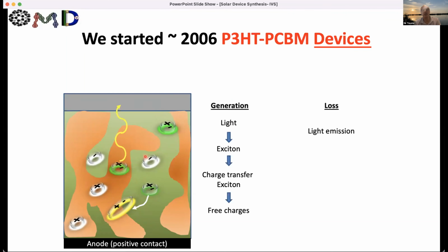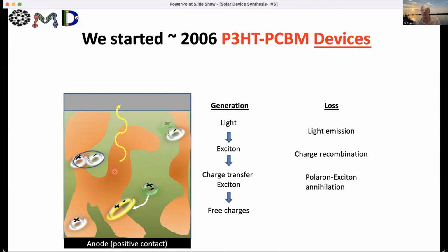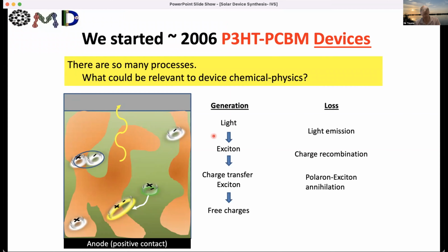And really we have the loss mechanisms. We have the trivial one, that there is always light emission accompanying absorption. We have charge recombination. Although we split them, they may find each other again and recombine. And there are some unique processes that are found in organics more than in inorganics, which we call charge-exciton annihilation. And there are loads of other processes that are not shown here, but this is really the essence. And the main thing is to try and filter out or synthesize the processes that we can tackle by designing a new device.